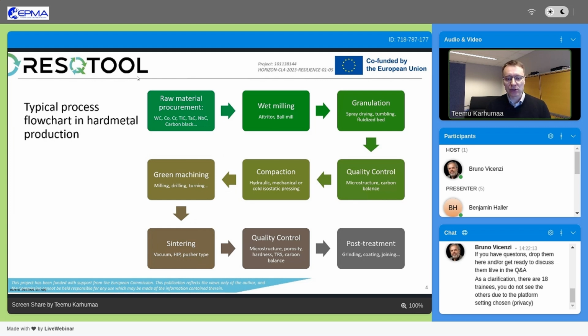And in my presentation, I don't cover the recycling which might be done within this process chain. So in many cases, some filter dusts are created during the spray drying of the hard metal slurry, and these powders are recycled back to the wet milling step. Or from green machining, you create powder which can also be put to the wet milling step. This recycling within the hard metal production chain I don't cover, but only the parts which are produced and used in the final application, like metal cutting inserts. They are used, they are worn, and then they are recycled back to raw material. And these recycling processes I try to cover in my presentation.